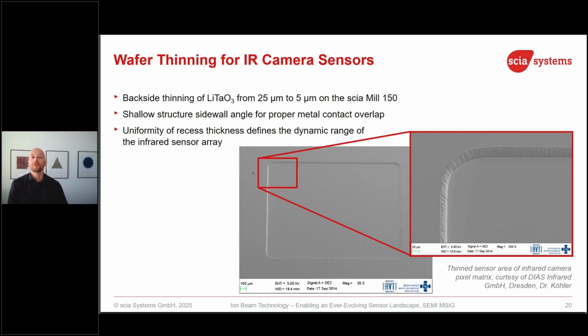Infrared sensors could be built out of lithium tantalate, which is a piezoelectric material. So when temperature changes, you get a voltage. And in order to have very sensitive sensor elements, they have to have a low thermal capacity, so those sensors need to be very thin. Lithium tantalate, you can't sputter it. You use a bare wafer, and then this one has to be thinned down by grinding and polishing. And our customer is doing it down to 5 micrometers.